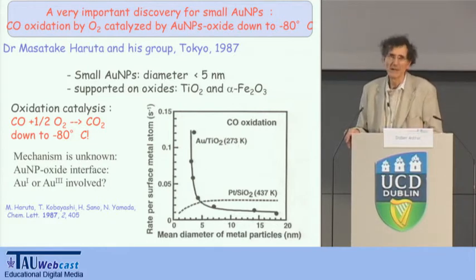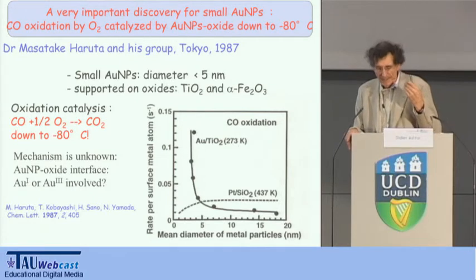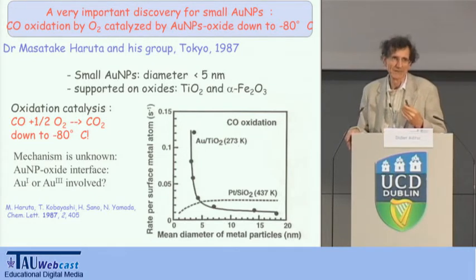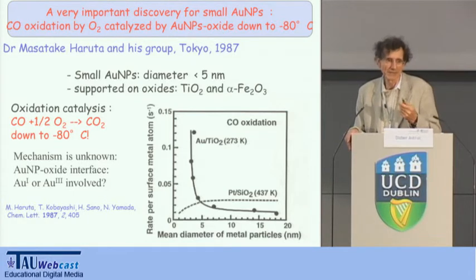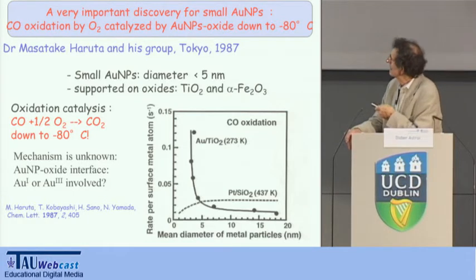And this very important reactivity was discovered if the nanoparticle is smaller than 5 nanometers. If it is larger than 5 nanometers, you don't get this catalysis. So you can see here the dependence on the size of a nanoparticle. If it is larger than 5, there's no reaction. If it is smaller than 5, it is very reactive.